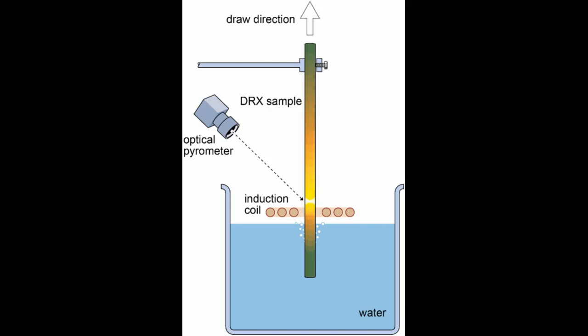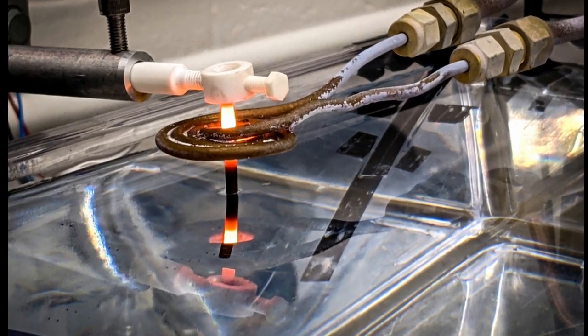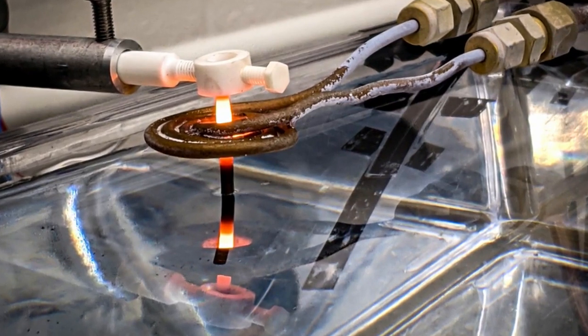In a series of experiments, the researchers placed 3D printed samples of rod-shaped superalloys in a room temperature water bath placed just below an induction coil. They slowly drew each rod out of the water and through the coil at various speeds, dramatically heating the rods to temperatures varying between 1200 and 1245 degrees Celsius. They found that drawing the rods at a particular speed, 2.5 millimeters per hour, and through a specific temperature, 1235 degrees Celsius, created a steep thermal gradient that triggered a transformation in the material's printed fine-grained microstructure.